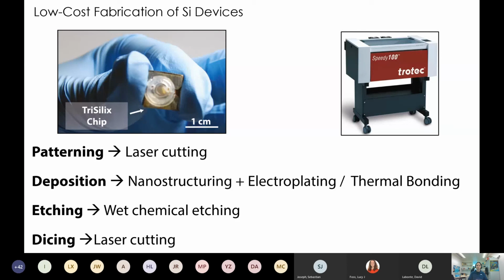So we said, okay, patterning is super important to make the devices. Can we replace patterning with laser cutting? Because laser cutters have become quite accessible nowadays. Deposition: can we somehow eliminate vacuum-based technologies and instead use solution-based nanostructuring and then electroplating and thermal bonding processes that could just be performed in our standard laboratory? And then etching: we would ideally just use wet etching to structure the substrate. And then once we make the devices at wafer scale, we don't want to use a diamond saw. Again, we use the same laser cutter that was used for patterning, for dicing and making the individual chips.